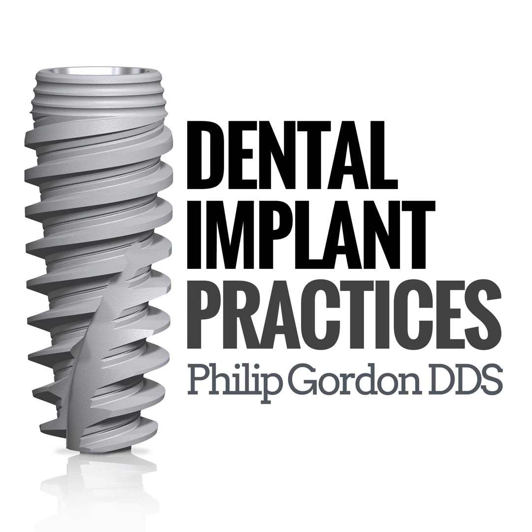So what I like about the nano ceramic is that it's monolithic. It's beautiful compared to acrylic, much stronger, and it's not porous like acrylic, so it's very hygienic. We offer basically 2 variations of the nano ceramic. When we temporize, we temporize with a nano ceramic, so we've got one material for the temporary process and another for the final restoration. The difference really is just the composition. The final nano ceramic has a higher ceramic content. It's very strong, but at the same time, it wears like natural teeth.